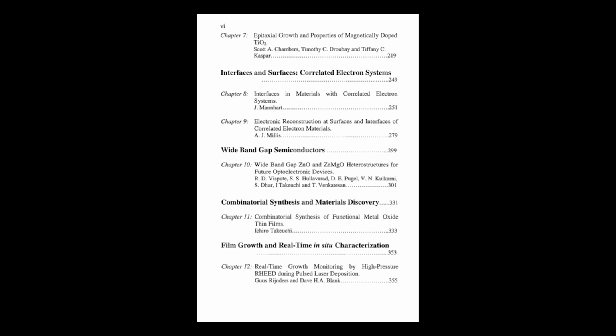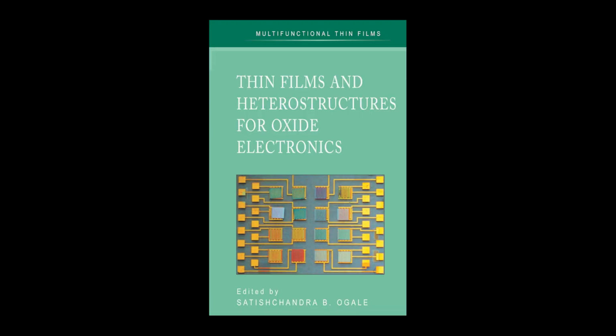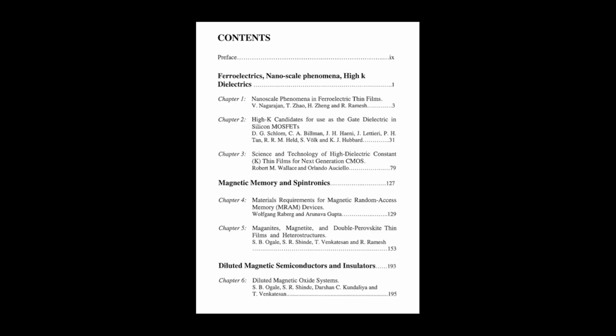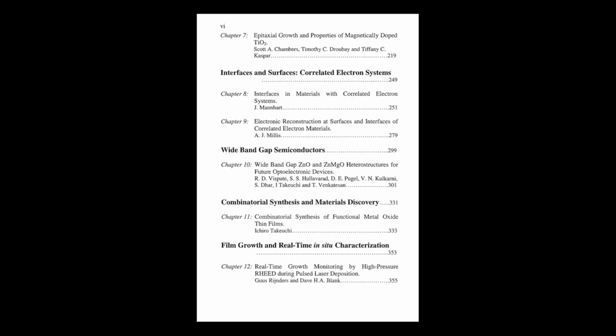Wow. Okay, so that chemical instability wiped out the early contenders. This forced a massive, really systematic search effort, didn't it? Oh, yeah. It was an incredibly thorough approach described in the source. First, they went through the periodic table, analyzing the thermodynamic stability of all binary oxides and nitrides against silicon. Everything. Pretty much everything remotely plausible. Right. Any element whose oxide or nitride calculation showed a negative delta G for reaction with silicon at 900 C crossed off the list immediately.